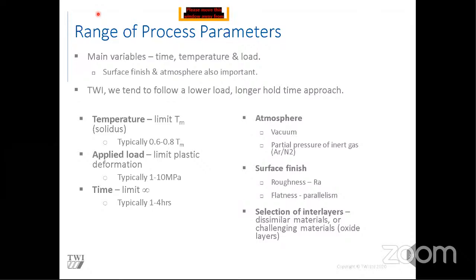Like I said before, we often do this in a vacuum or a partial pressure of inert gas. The surface roughness parameters which are important are the surface roughness, or RA - the smoother the surface, the better the diffusion bonded joint afterwards. But flatness and parallelism are also very important. You can have a very smooth surface, but if it's not parallel with the face you're trying to join, you're going to get a huge void present. So surface finish is very important.